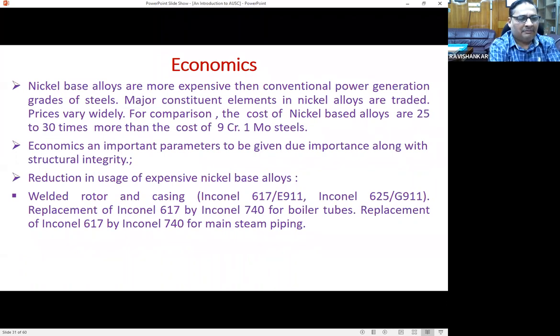So economics became an important parameter, and that led to the change of the material of construction. In Coral, as you can see, sir, boiler tubes we replaced by 740, and the mainstream piping we replaced by 740. The 740 could not be used for hot reheat applications, sir, because the pipe size manufacturing was not possible for the requirements, sir. So that's why we had to be content with 617. That we have retained, 617 only, sir.